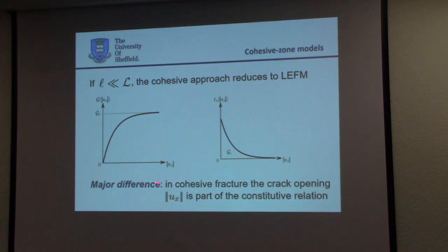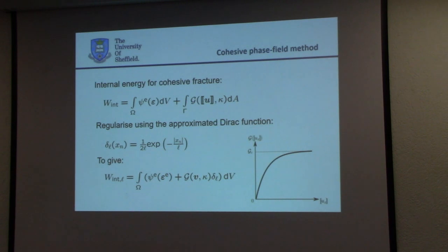So the bottom line is when you look into the cohesive approach to fracture, the crack opening is a part of the constitutive relation. And that's not the case in LEFM. And in fact, you can also formulate a phase-field model for cohesive fracture.